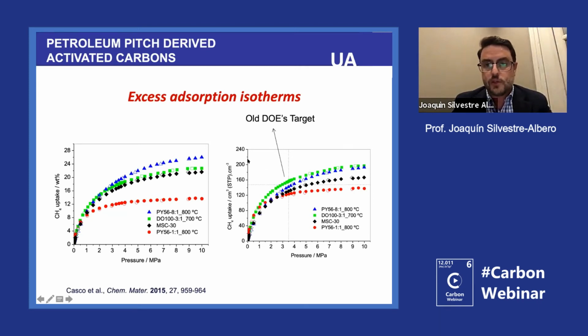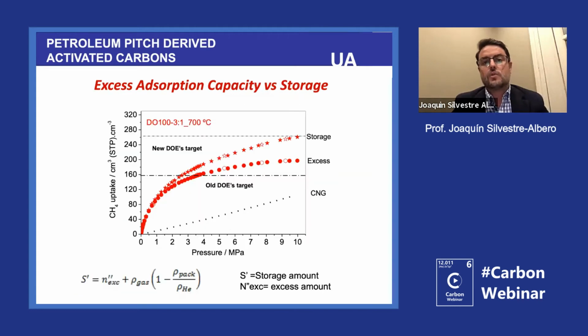If you look at the values that we obtained with this type of carbons that we were developing from petroleum pitch, you can see that our maximum was 200 volumes per volume. So this is lower than the theoretical DOE value, which, as I told you before, is 263. But this is the isotherm that we get from the system, the excess adsorption isotherm. And we know that the DOE target refers to the absolute amount adsorbed. So we have to apply this equation here at the bottom to convert the excess into storage. And when we apply this equation to this sample with 1:3 activation, you see that we managed to reach 263 volumes. So that was the DOE target, but at 10 megapascals. This is more or less in close agreement with the theoretical predictions. Carbon materials can reach these values, but we have to go up to 100 bars as a minimum pressure.